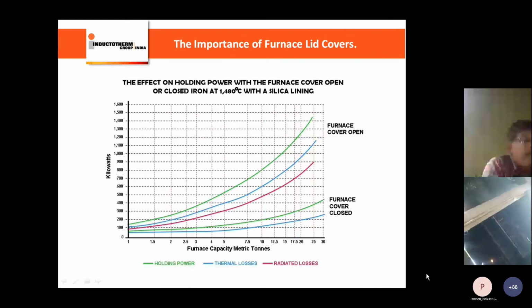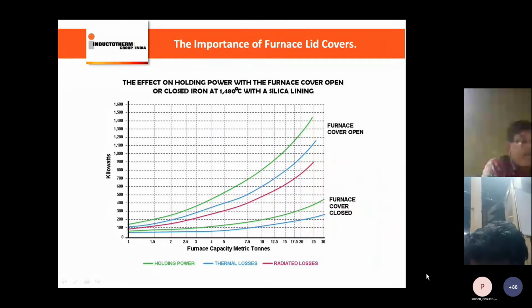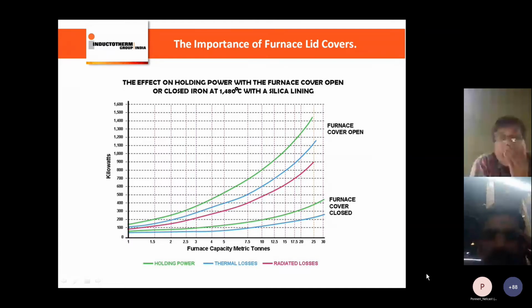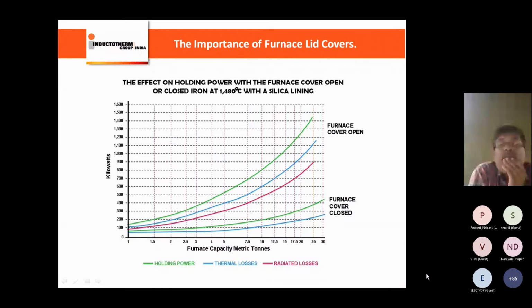So that is the feed rate we talked about. And we need to understand the importance of the lid covers. We have been supplying lid covers and vortex fume hoods with fume rings. When the furnace is operating with the lid cover on and with the lid cover off, the holding power is different. Let us take a 5 ton capacity induction furnace. When the lid is closed, the typical holding power requirement is about 150 kilowatt or 125 kilowatt to maintain the same 1500 degrees temperature. Whereas when the lid is open, it becomes almost 2.5 times. So in order to avoid these radiation losses, first and foremost, every furnace should have these lid covers.